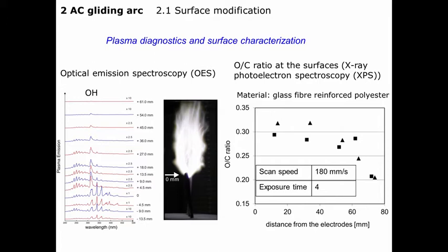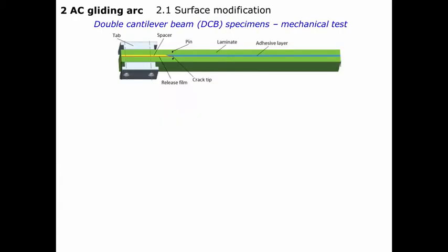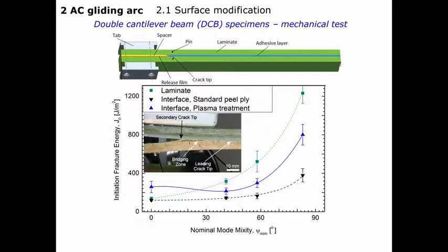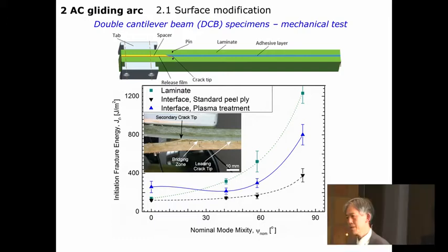And at the same time, I treated the specimen and measured the atomic elements on the surfaces, how it is oxidized. Then even up to around 6 centimeters, the surface is nicely oxidized. So these are kind of nice, happy agreements between the plasma diagnostics and the surface characterization. And then we jumped into the mechanical tests, having this nicely designed setup of the sandwich specimen called double cantilever beam specimen, treating both sides and having glue and cured, then make various different moments of opening and shear stress.